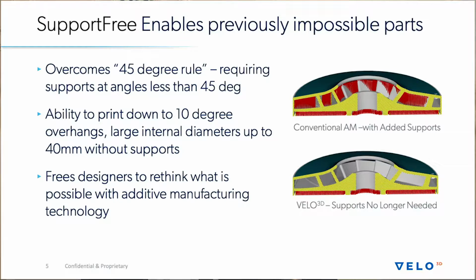So you may have heard us talk about support-free manufacturing, and I think it's useful to give an idea of what we mean by support-free manufacturing. So in metal additive, there's the standard 45-degree rule, which is overhangs that are 45 degrees or lower from the build plate generally need supports. And people have done a lot of work to push this to lower angles, depending on material and geometry. But there's still a lot of limitations around what can be printed and what supports you can actually eliminate.